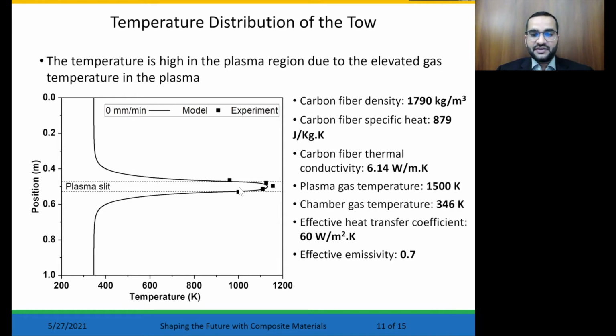The tow temperature increases gradually in the pre-plasma region, maximizes in the plasma region, and finally decreases in the post-plasma region. The temperature is high in the plasma region because of the high plasma gas temperature. Heat is conducted from the high temperature region to the lower temperature regions, until the tow temperature equilibrates with the gas temperature in the vacuum chamber.